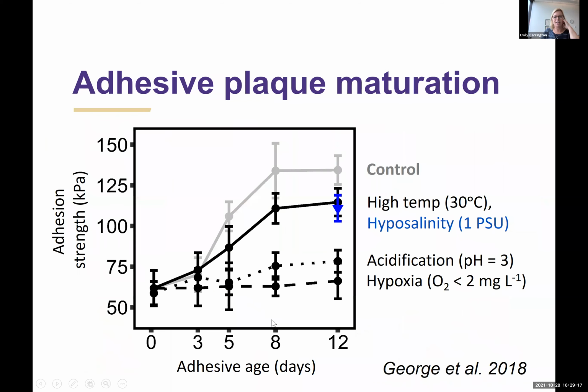So what Matt was able to do then was to take byssal threads that were made in normal seawater, but then incubate the adhesives in different water conditions for up to 12 days. When they were in control seawater, normal pH, normal oxygen, you can see that they increase in strength. It takes quite a long time, about a week, for them to get fully strong, and that's about a 2.5-fold increase in adhesive strength.